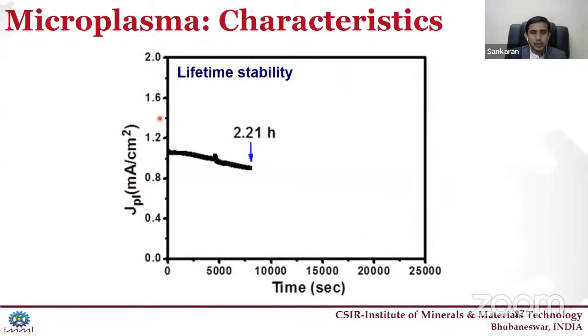When you are taking a cathode material, people are working on, still we are working on this to get a high lifetime cathode material. When you are talking about electron emission, even when field electron emission occurs for the FESEM or maybe for the transmission electron microscopy, the lifetime of those cathodes, like LaB6 or carbon nanotubes, is degraded in a few years or maybe in a few months. So we need a very stable cathode material for electron emission when you're talking about the primary electrons. But when you're talking about the microplasma, the plasma can etch out the cathode material very easily. So the lifetime of that material is degraded very quickly.